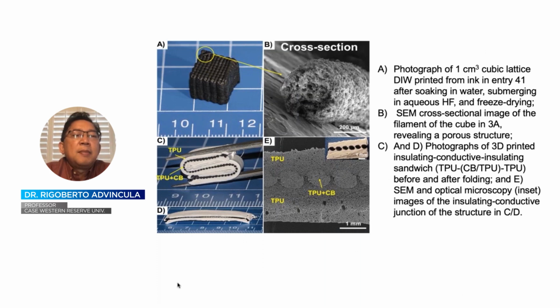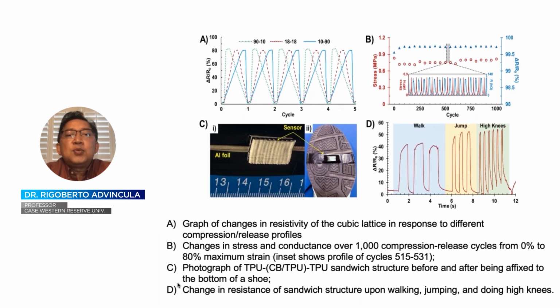We can sandwich thermoplastic polyurethane and the carbon black containing thermoplastic polyurethane, as well as induce the porosity based on the amount of porogens we added to the material. The result is we have a sensing material. In fact, this is a sensing material for motion. So in this case, we loaded up the sensor material as shown in C on a shoe sole, and then we walk, we jump, we bend, and you can see the change in stress or the response as shown in graph D.